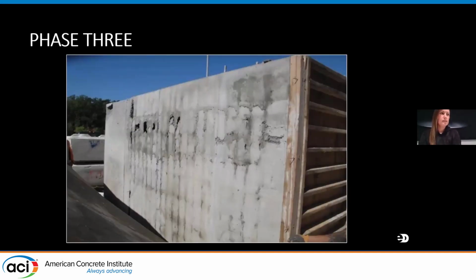And then upon the examination of the stripped faces of the second mock-up, it was apparent that they were unable to achieve proper consolidation of the shotcrete right to the back of the wall. While the side faces of the mock-up appeared reasonably well consolidated, the back faces did not achieve the same level of quality. It seems as though the nozzlemen were unable to get the shotcrete to effectively penetrate beyond the back rows of the reinforcement and encapsulate it.